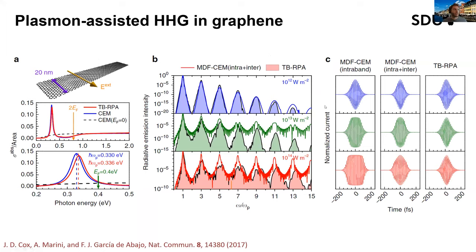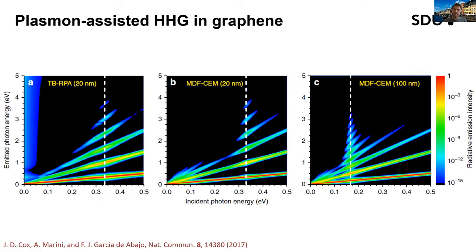And then we can look, of course, at harmonic generation, if we simulate interaction of a graphene ribbon, for example, with an intense light pulse. What we can do is target the central frequency of the pulse so it matches the plasmon resonance, and then see that indeed you have a huge boost in harmonic generation. We compared this atomistic modeling with the modeling for an extended system, solving semiconductor Bloch equations and then building in the field enhancement. And it does work well up to a point. In the atomistic model, you take into account the saturation of the near field enhancement more accurately. So we see a little bit of a damping compared to the extended model. But overall, qualitatively, it's a great description.